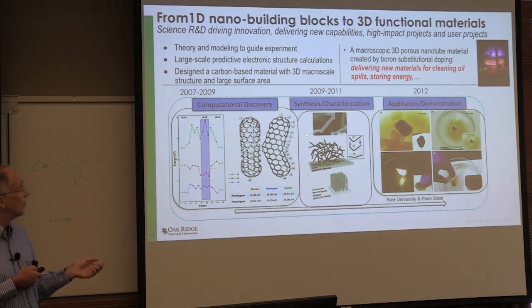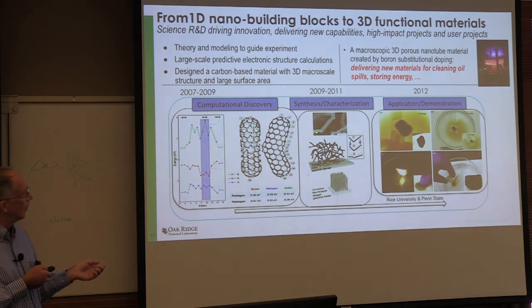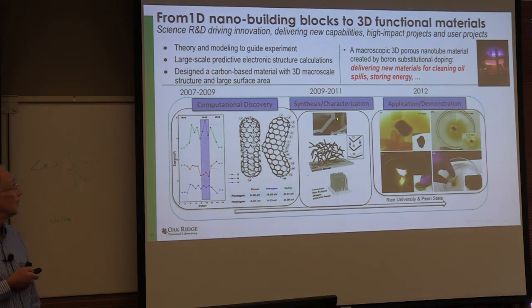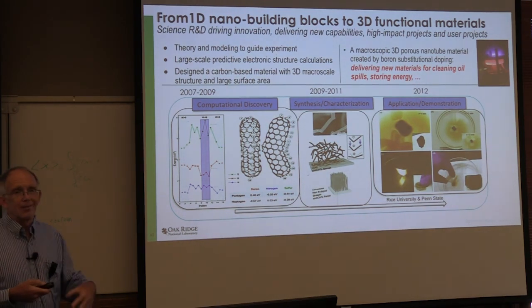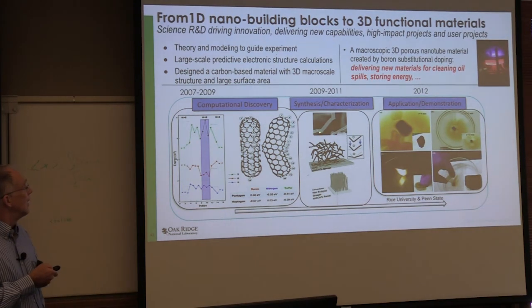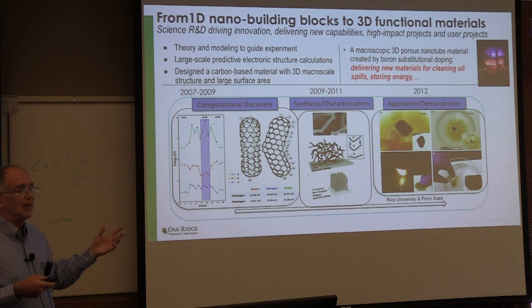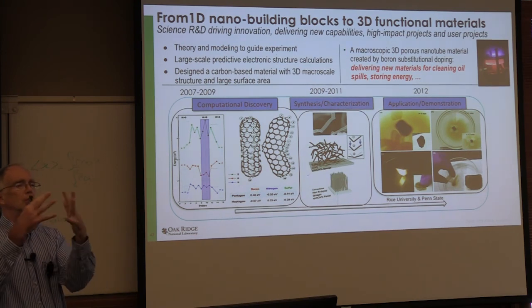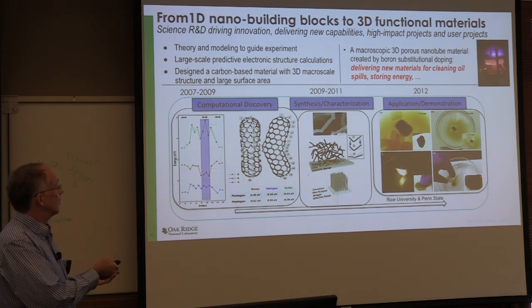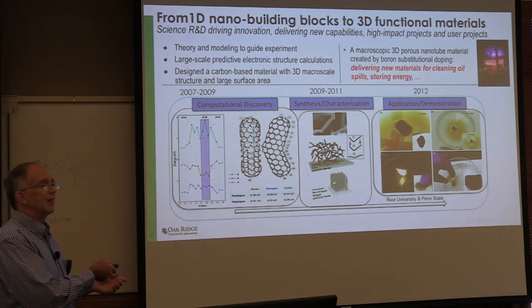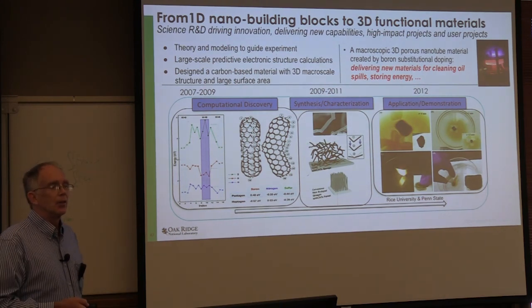And lo and behold, gee whiz, that's an actual experimental image of one of the carbon nanotubes. So you get all those elbows with the boron in there. Without the boron in there, you don't. So it works, right? The synthesis process can be continued on, and in the end, you get a network of entangled tubes that basically looks something like that, ideally, versus when you don't have the boron in, you just get this array of straight tubes.